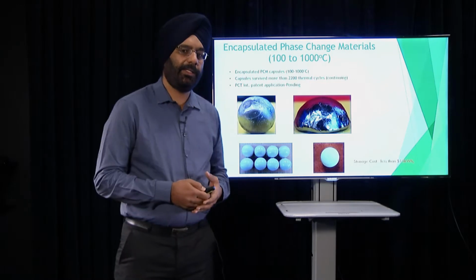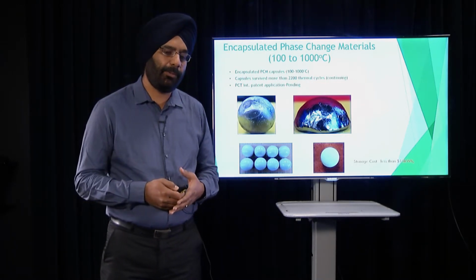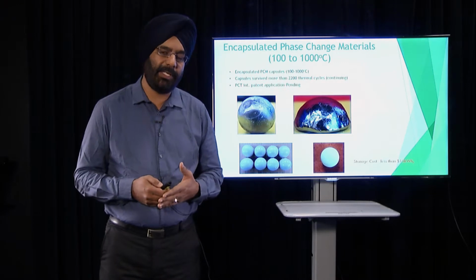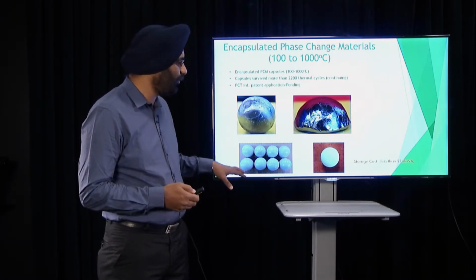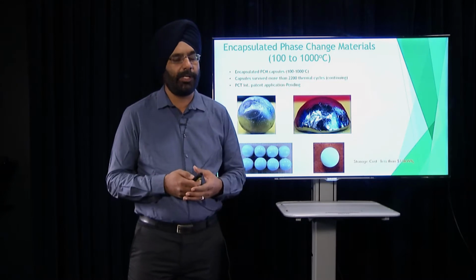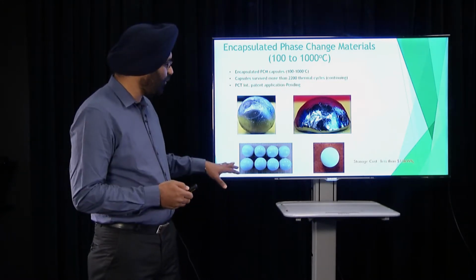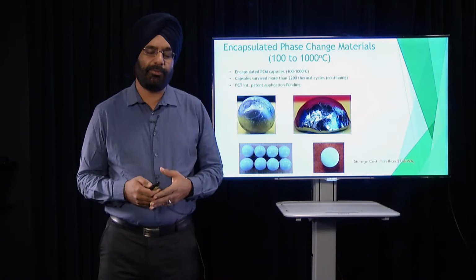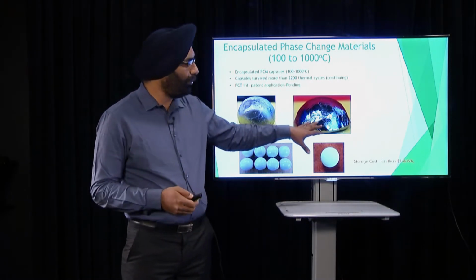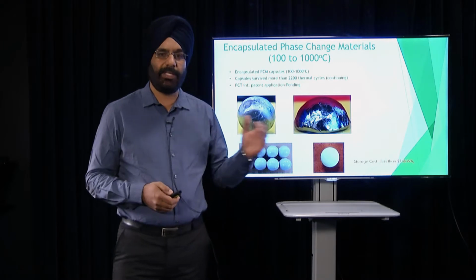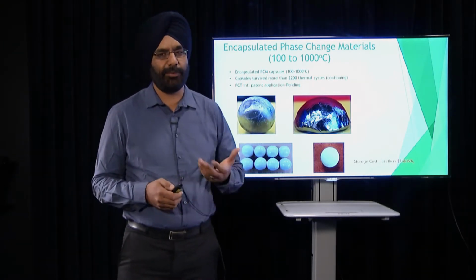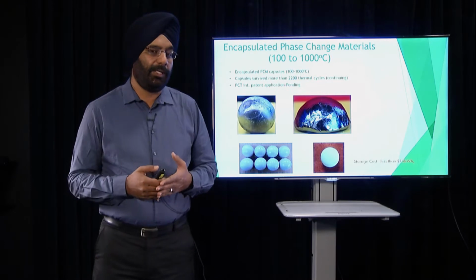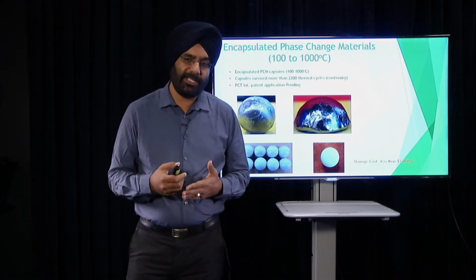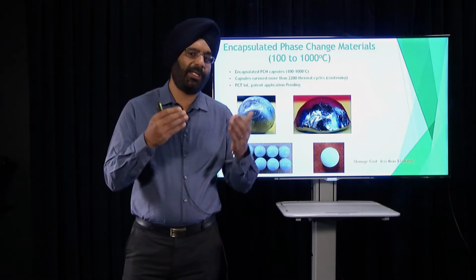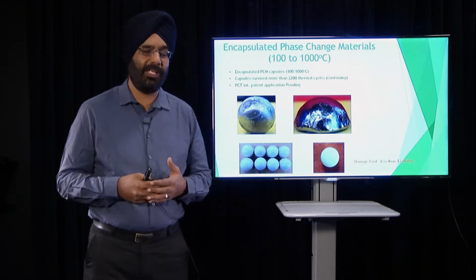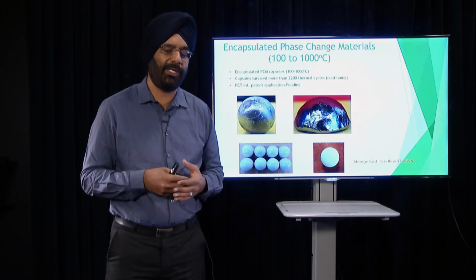Not only the capsules which had the polymer and the metal coating, we also fabricated some capsules which were made of ceramics. Now these capsules had a specific reason. These capsules work at much higher temperature than our metal coated or polymer coated capsules. Their temperature range is around 400 degrees C or at most 450 degrees C. But the direction in which this technology is going is higher temperature, 600 degrees C, 800 degrees C, or no one knows, it may even be 1000 degrees C.